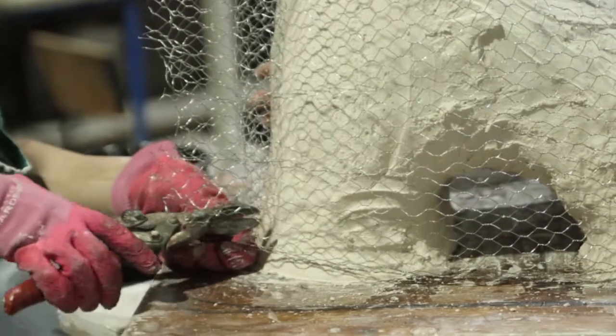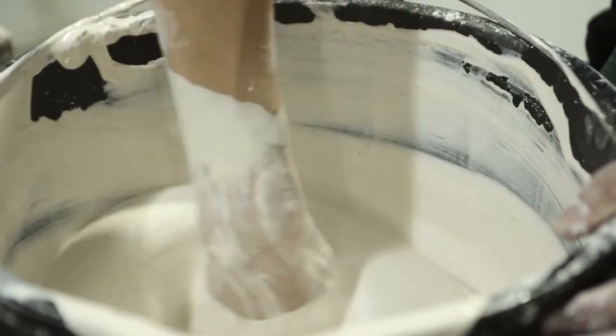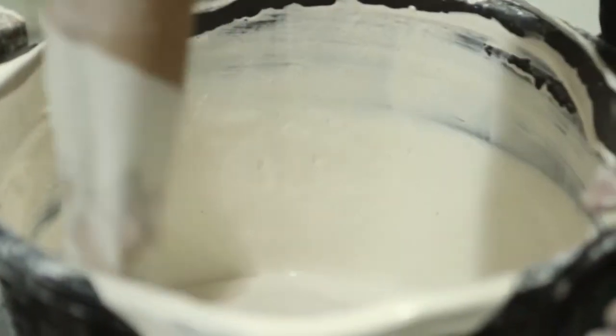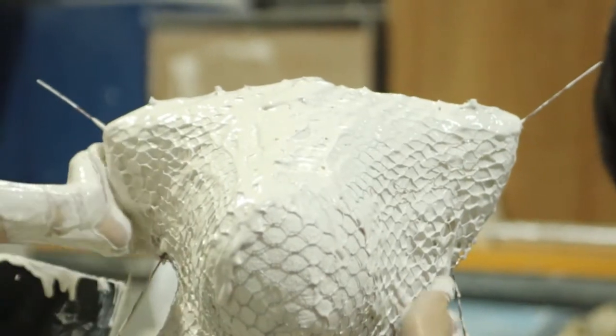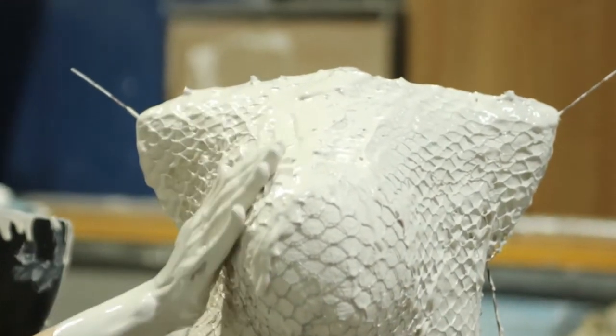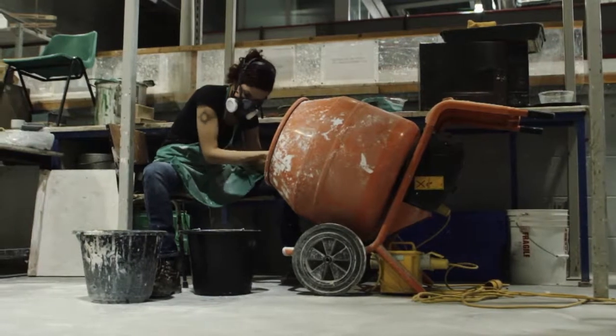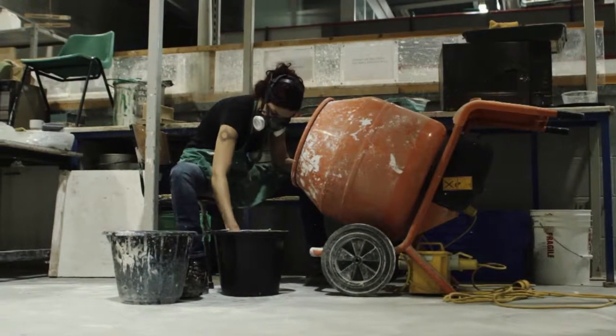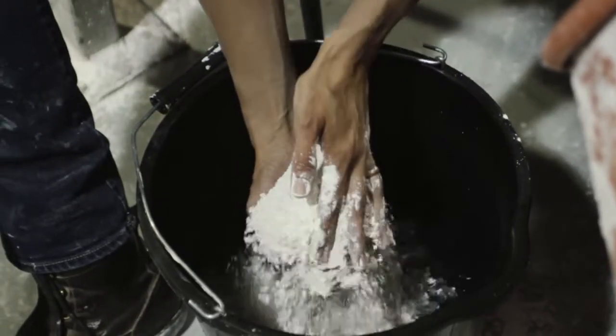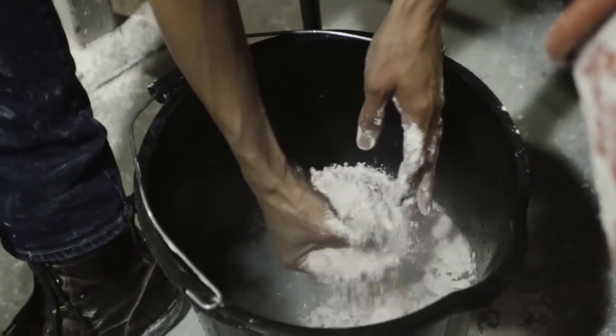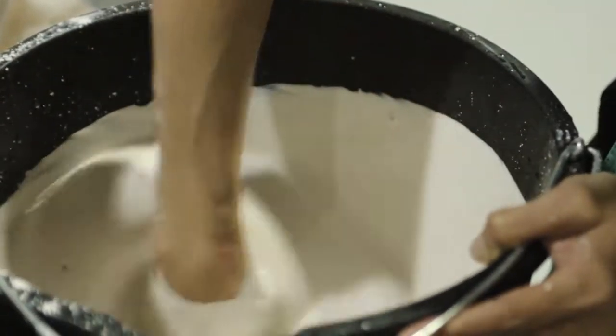Since we're talking about a very, very big project, I'm trying to put as many refractory materials into the mix, so I can essentially end up with a mold which is not thicker than 15 centimeters all the way around. The mix I use is plaster and silica. I normally use more silica than plaster, so for about 1 bag of 25 silica I would use about 21 kilos of plaster, and that is because I want the mold to be quite soft, and I want it to give, because there's a big undercut in the model itself, and I want the mold to be able to shrink with the glass and to move with the glass.